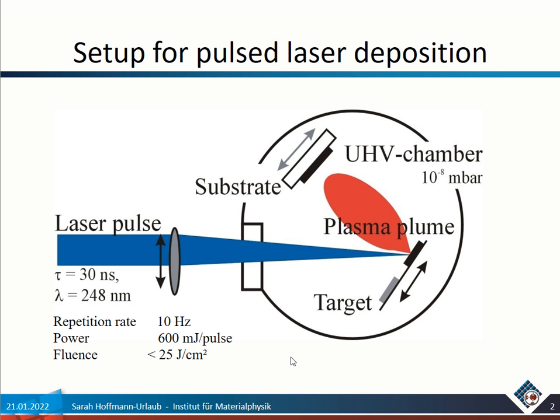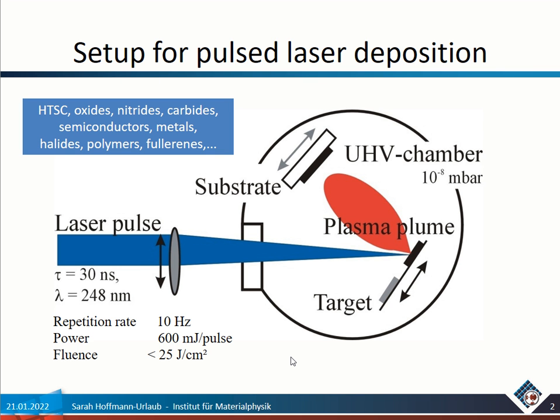What is interesting with this pulsed laser deposition is that you can apply this technique to any kind of material. The main focus in the 80s was on high temperature superconductors. There this technique became very famous, but also oxides, nitrides, carbides, semiconductors, metals for sure, but also other things like halides, polymers and fullerenes can be deposited using this technique. Here we also have the tremendous advantage that the deposition source, the laser, is outside the chamber itself, so you don't have any back coupling from the actual deposition process to your source, like in sputtering techniques. And this is why you can have such a variety of different materials.